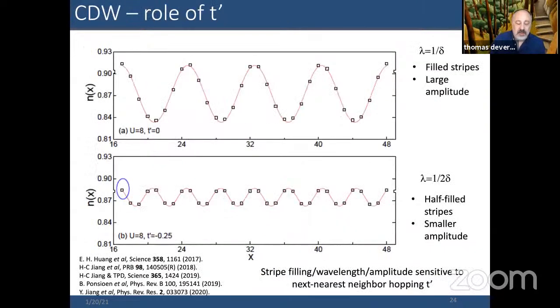I think though a lot of emphasis has been put on the role of T prime, and in fact, it's one of the strongest parameters that can change the behavior of the order. So above is the period eight stripes that one gets with T prime equal to zero. Here's a different value of U equal to eight. One puts on a T prime, here T prime is minus a quarter, you can see right away that the period is halved. So one goes from filled stripes, all the holes being on the stripes, to half-filled stripes distributed with half the distance between them. But also importantly the amplitude of the charge density modulation comes down as well.